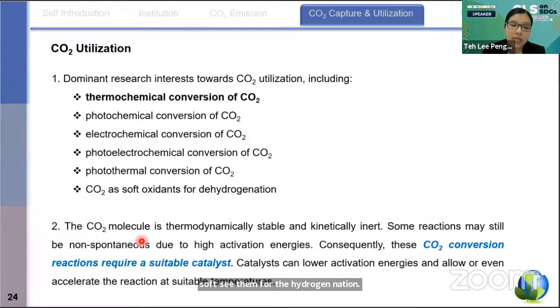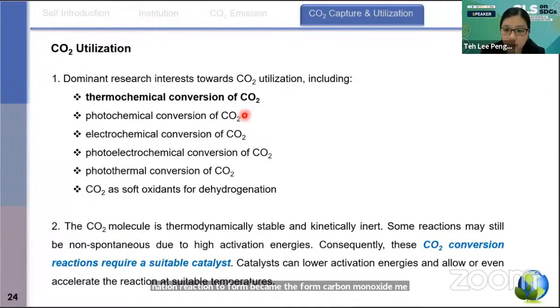Basically, the CO2 molecule is thermodynamically stable and kinetically inert. So some reactions may still be non-spontaneous due to their high activation energy. Therefore, for CO2 conversion, we require a very suitable catalyst. The catalyst can lower the activation energy and allow or even accelerate the reaction at a suitable temperature. For today's sharing, I will focus on the thermochemical conversion of CO2, especially the CO2 hydrogenation reaction to form methane, carbon monoxide, methanol, and several hydrocarbons.